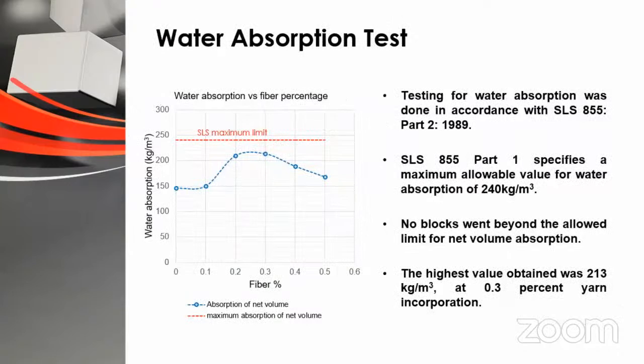Water absorption test. Testing for water absorption on cement blocks is done to evaluate the block's weather resistance and other durability factors. SLS 855 Part 1 establishes 240 kg per cubic meter as the maximum permitted value for water absorption. As in the graph, no blocks exceeded the permitted threshold for net volume absorption. The highest number for water absorption was 213 kg per cubic meter with a yarn inclusion of 0.3%.